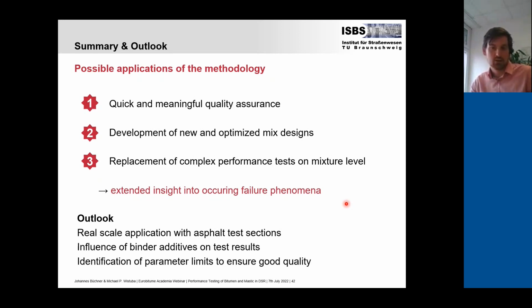The outlook is that we are looking at real scale application, also working together with the companies to look at how the change with aging during the mixing and compaction and after compaction can be applied there or not, to look at different binder additives and their influence on the test results, and to identify parameter limits to ensure good quality, because now we only have correlations, but we don't know where the limit is. Maybe we need at least 90% of relaxation in order to avoid any cracking at low temperatures.